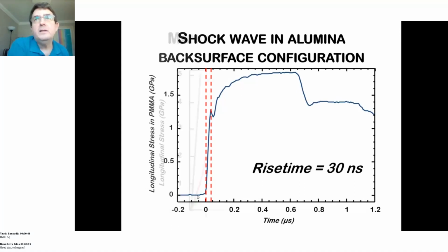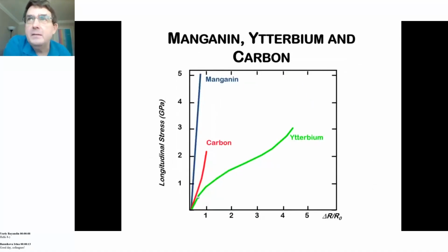If we want to look in a little bit more depth about how manganin behaves itself, then we have manganin, its stress versus change in resistance here, showing it does not have a super large change in resistance with pressure.